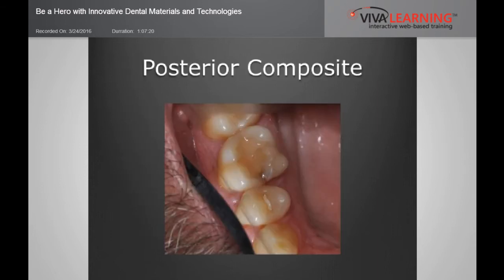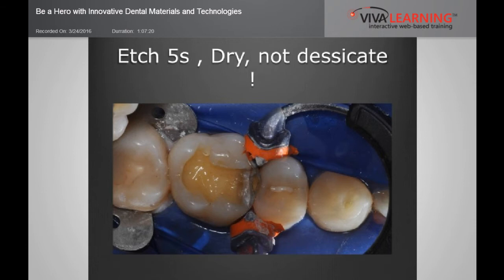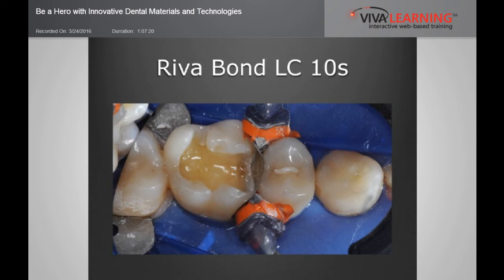Okay, posterior composite. This is a real case, a real clinical situation. Basically, what we get over there, I did the prep, and I'm a strong believer in rubber dam. Very often, this is the fastest way to get the best isolation possible. So what I did, etch for 5 seconds, dry the tooth, but do not desiccate the tooth. We can see it's a little bit wet on the dentin surface. Then what I do, I put the Rivabond in a thin layer, remove the excess with a second micro brush, then cure it. And after that, you can put the composite of your choice.